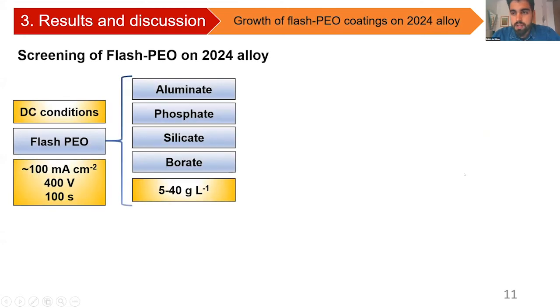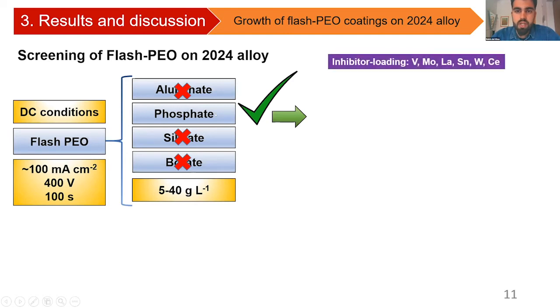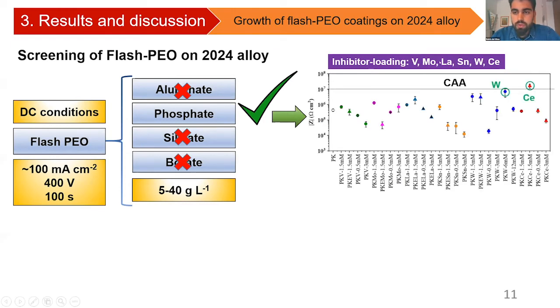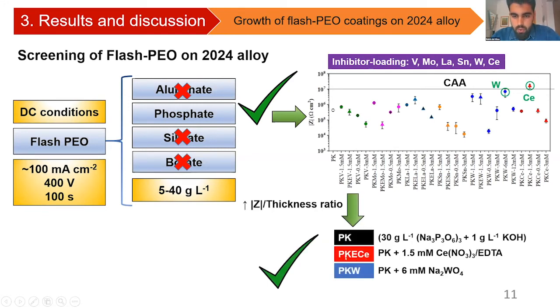For this, our first stage was a screening process using low current densities, a voltage limitation, and short treatment times in different electrolytes. After the first screening process, based on the electrochemical measurements, we concluded that phosphate electrolyte is the most suitable to study inhibitor loading processes. We studied vanadate, molybdate, lanthanum, tin, tungstate, and cerium. According to the impedance modulus during 1 hour of immersion in sodium chloride solution, we concluded that cerium-containing and tungstate-containing flash PEO coatings were the most corrosion resistant. So for this reason, these coatings were selected for further analysis.